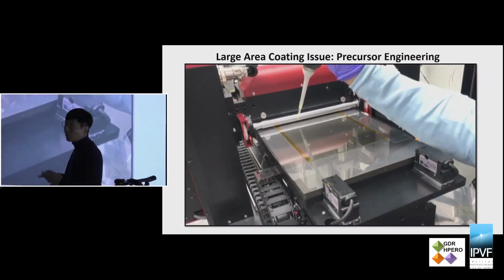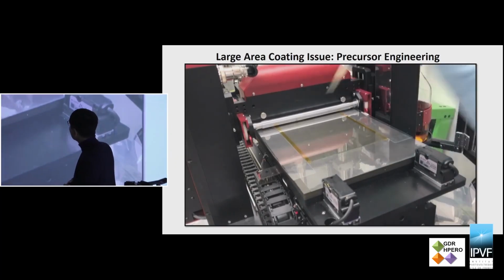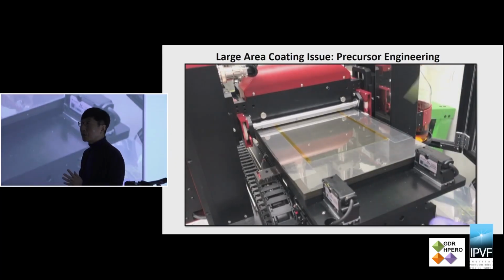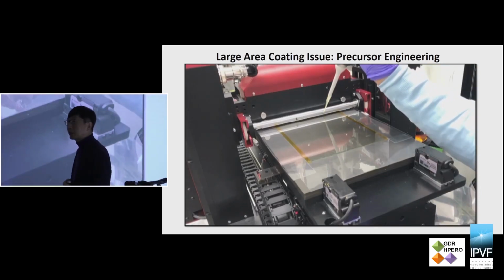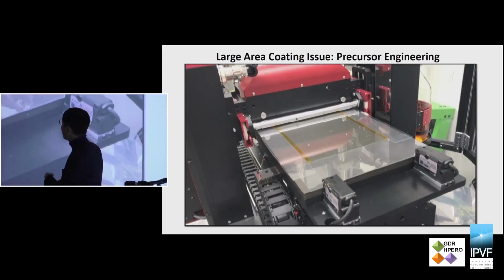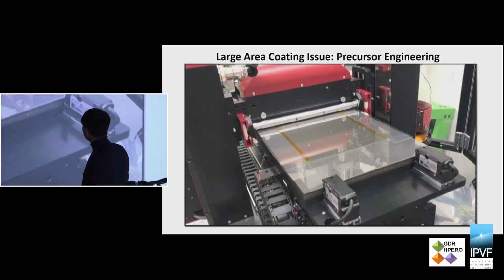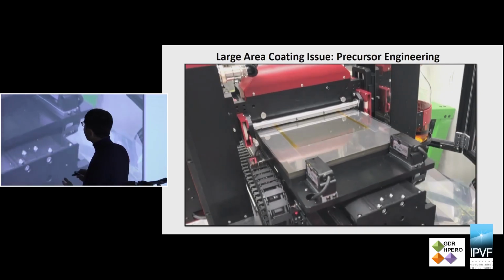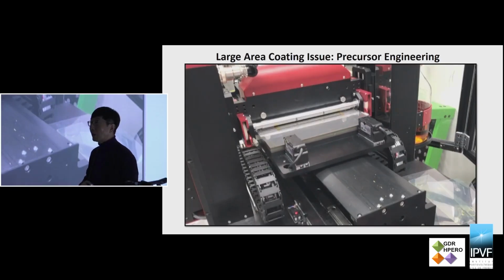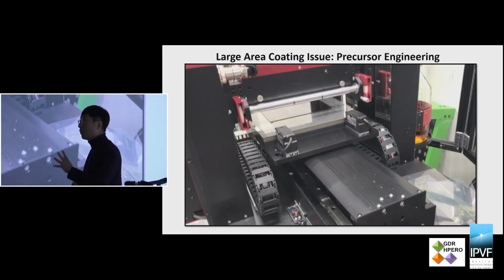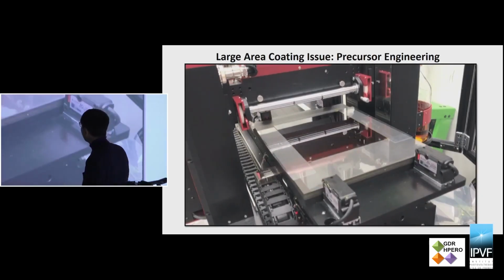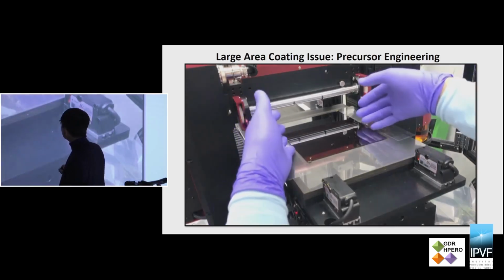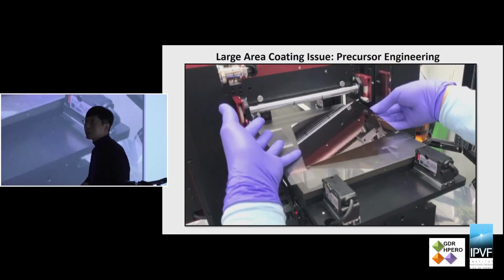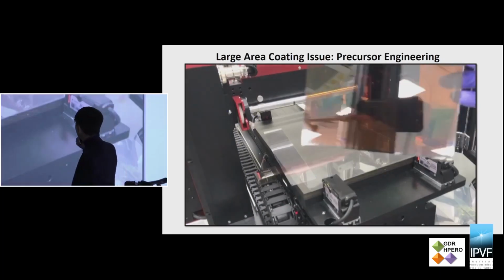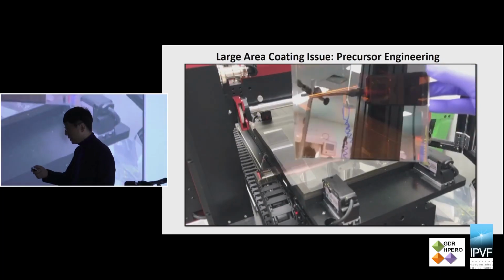For large area coating, we need a very specific coating solution, different from the technology used for spin coating. So we developed a very special coating solution without polar aprotic solvents such as DMSO or DMF. We use acetonitrile, and this is a room temperature coating. You can see that immediately we can have a very good perovskite film.